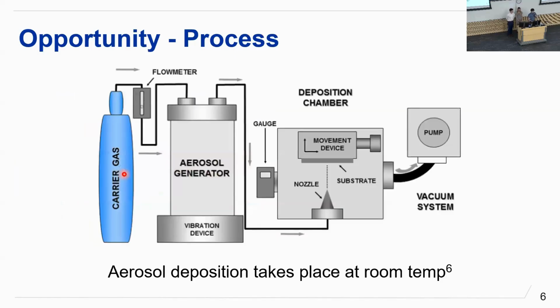And the process that we use is called aerosol deposition. This process takes place at room temperature, so there should be no phase changes present. And how it works is that the carrier gas, and for us, we use nitrogen, goes into where our powder is and aerosolizes our powder. And that aerosolized powder is then accelerated, focused at the nozzle, and accelerated towards the substrate as the substrate moves on the XY axis and is programmable.